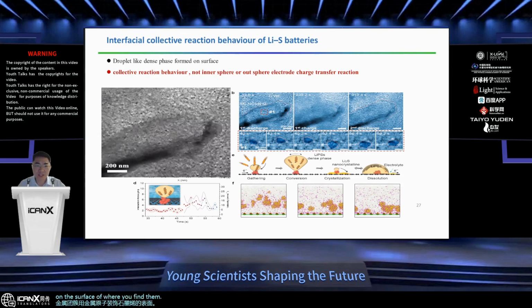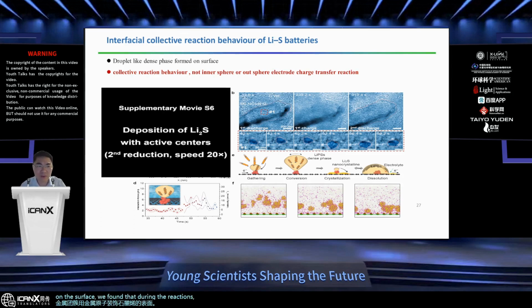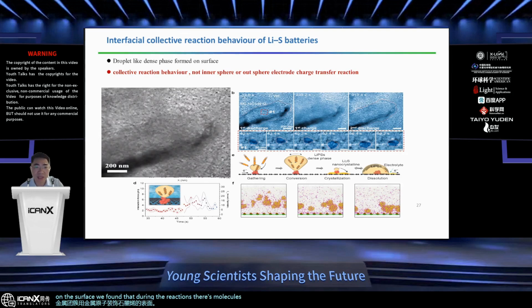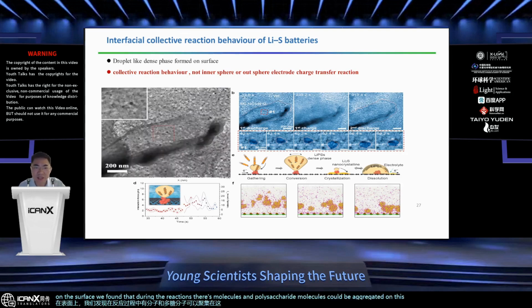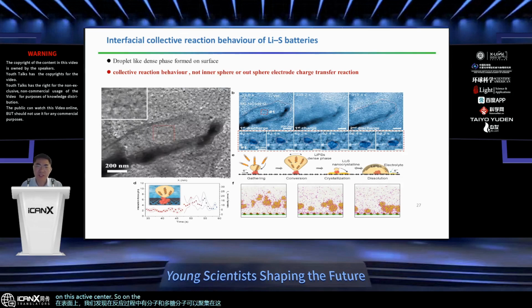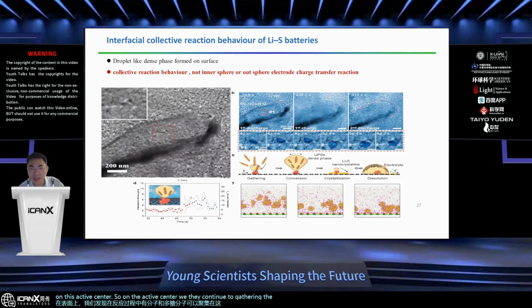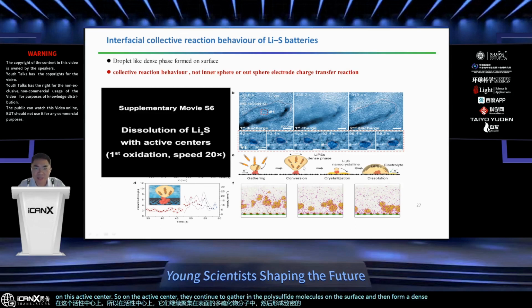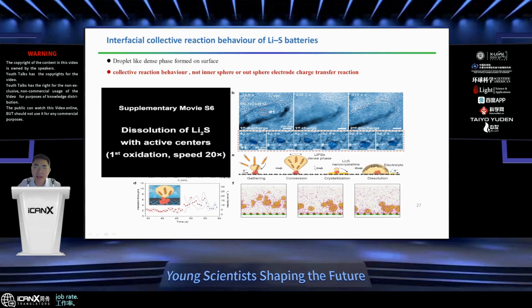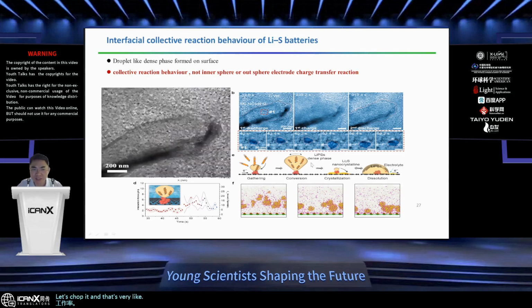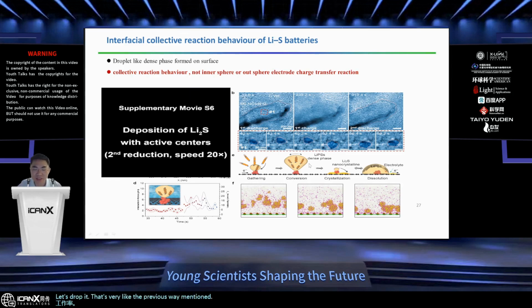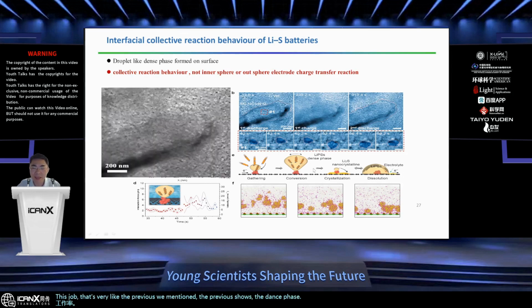We found that during the reactions, polysulfide molecules could be aggregated on this active center. On the active center, they continue gathering polysulfide molecules on the surface, and then form a dense phase, a droplet-like droplet. This droplet is very much like the previous one we mentioned, which showed the dense phase around the nanoparticle surface.